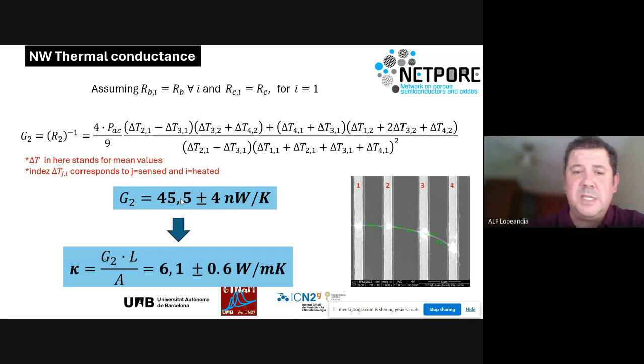Something that is good, because as I said before, the final uncertainty on the thermal conductivity will be essentially driven by the determination of the area, by the determination of the diameter of the wire. And we got, with a method able to determine the thermal conductivity of the nanowire without taking into account the contact resistance, a precision in the determination of the thermal conductance better than the uncertainty that we will introduce on the thermal conductivity through the geometrical parameters.